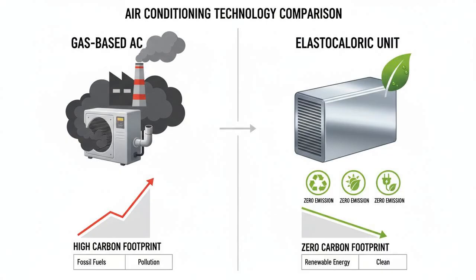Why go through the trouble of reinventing the fridge? The answer lies in two metrics: the coefficient of performance, or COP, and the global warming potential, or GWP. Vapor compression is mature. It has been optimized for 100 years, yet it is hitting a theoretical wall. Theoretical studies suggest elastocaloric materials can achieve 60 to 80% of the Carnot limit, which is the maximum theoretical efficiency allowed by physics. Traditional AC units typically operate at only 40 to 50% of this limit.